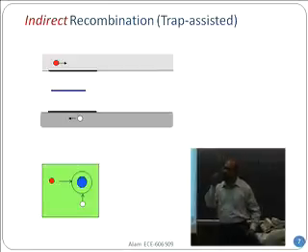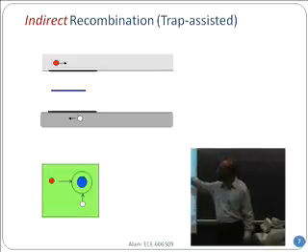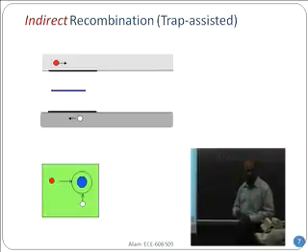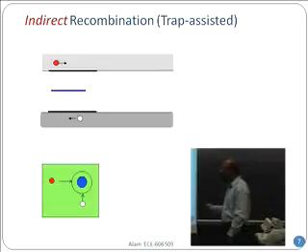The reason is even a tiny fraction of the copper, if it could escape and go down into the transistor underneath, your whole IC will die right there. So not even a tiny fraction of copper is allowed to escape down, because this will immediately kill your transistor because of this recombination process, right? Gold and copper in silicon, but other materials will have different levels.